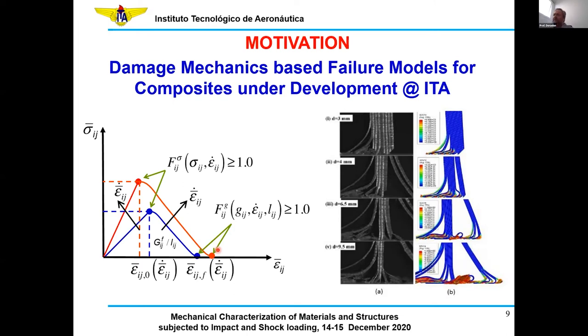And all of that is trying to understand and predict, as much as we can, in a very high fidelity way, the behavior of the composite under different loading conditions. On the right-hand side, you have some images showing a crashing simulation and a comparison with the experiments that we have performed here at ITA. As we can see, we have a fairly good correlation, not only in terms of structural response, but also in terms of damage morphology. This is because, as I mentioned before, we try in a very deep way to understand how damage initiates and how damage progresses within each ply of the composite under study.